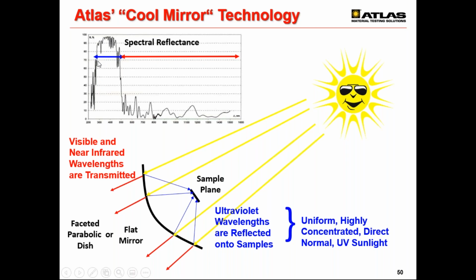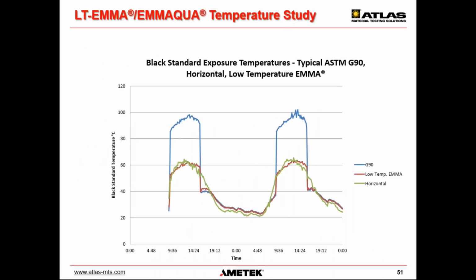And to show you what this looks like as far as the spectral reflectance, you'll see this graphic right here. So what's really being reflected is all of the radiant energy from the solar cut-on at this 295 nanometer point up to about 450 to 500 nanometers. Almost everything else is transmitted through, and this is what allows for those cooler temperatures on this low temperature EMMAQUA type of device. This shows you an example of what those temperatures look like. Here is a standard G90 exposure with a black standard. So this would be an insulated or backed black panel exposed on a traditional EMMAQUA type of exposure. And here are the temperatures for the low temperature EMMAQUA, as well as a black standard exposed just in a horizontal exposure out in the static weathering field. And as you can see, the temperatures are very consistent. This is over the course of 2 days.